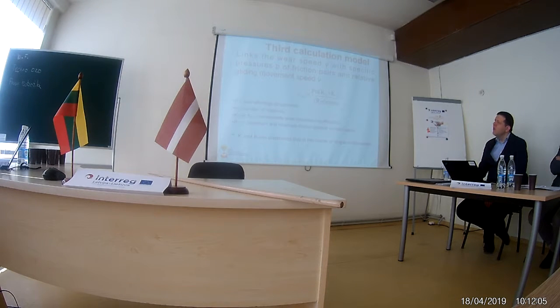The third calculation model is more closely connected with, say, more simple parameters, and it involves pressure of friction pairs and relative gliding or sliding movement speed. So you can see that here we already have such parameters as number of rotations, loading effect components, but we also have such parameters as T1 and T2, which are determined only in the course of a long-term experiment. So, what is the use of this equation if we need to make a long-term experiment? We can state the actual fitting life after the experiment, without using this equation for calculations.